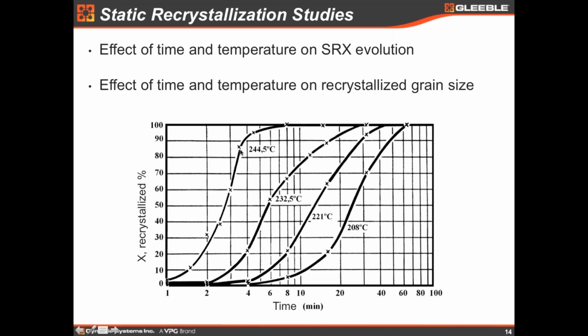And I take all the specimens, I go to the lab, I mount the specimen, I grind, polish, etch, look at the microscope and do the quantitative metallography, and then I see how much is the recrystallized fraction. So I have the first curve. So this is a very simple heat treatment.